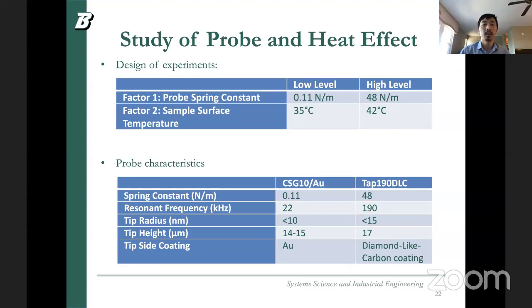We designed a two-level factorial design with two factors. Factor one is probe spring constant: one is a very soft probe, and one is a very stiff probe. And then we designed two different surface temperatures, 35 degrees C and 42. The most important thing here is the spring constant. Those are some other characteristics here.